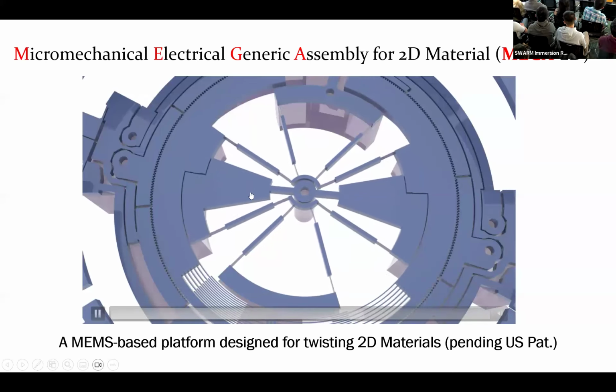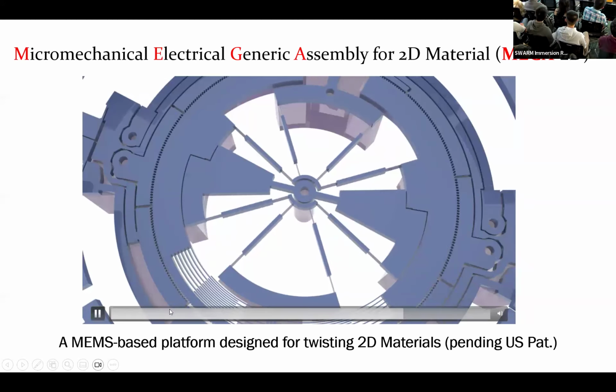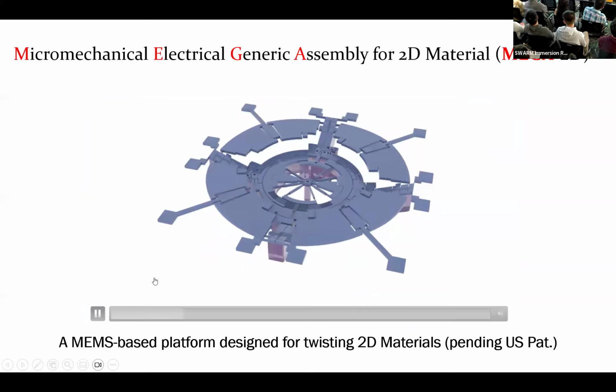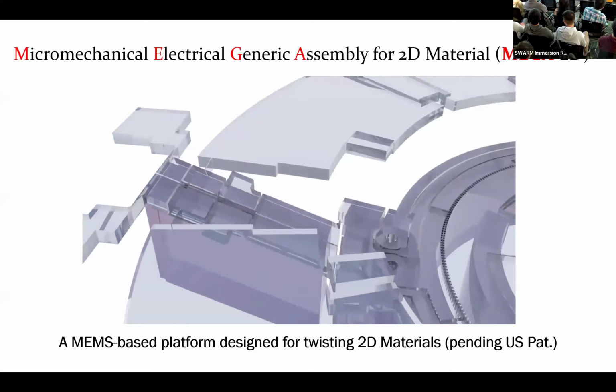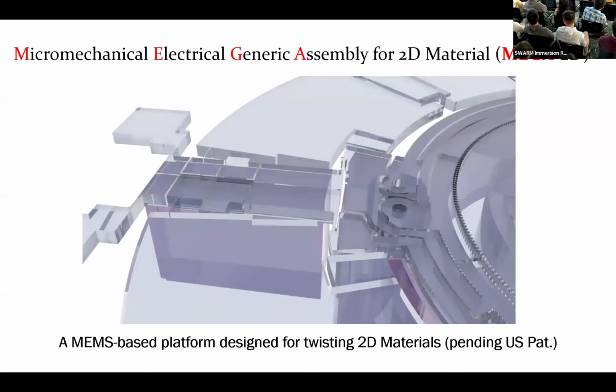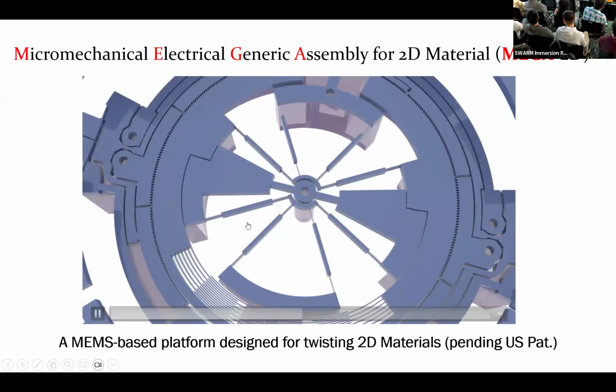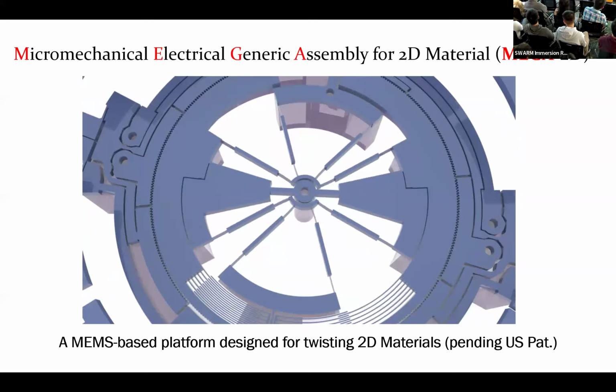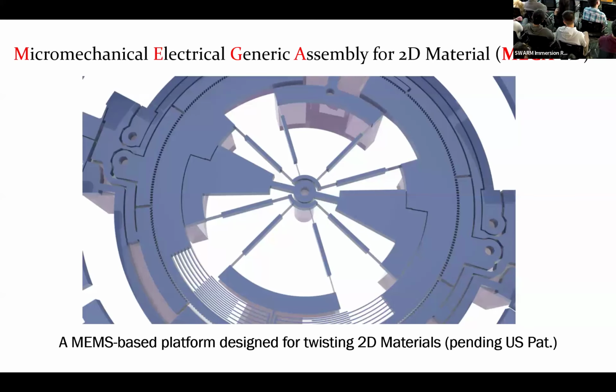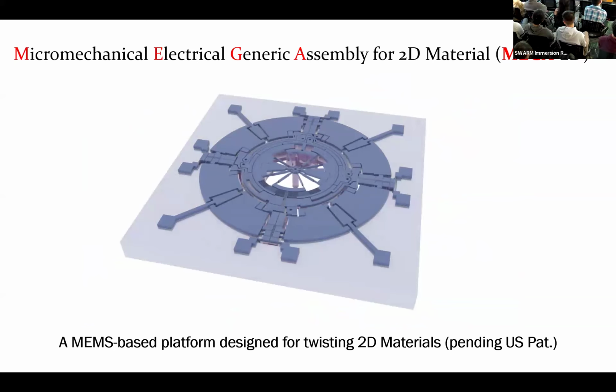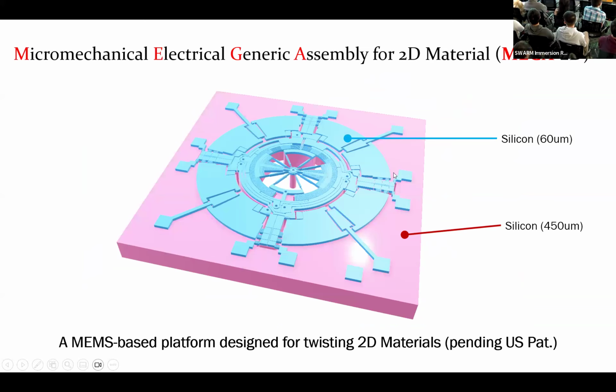So what we have is a device like this, where it has 2 degrees of freedom. One is a vertical translation, and the other one is the rotation. And these are all actuated by electrostatic actuators, both the vertical and the rotational one. And these are all via flexural suspension, so there is no hysteresis and things like that. So this is a platform that we designed from scratch to be able to study twisted 2D materials. It's fabricated purely from silicon, both the device and the handle layer.